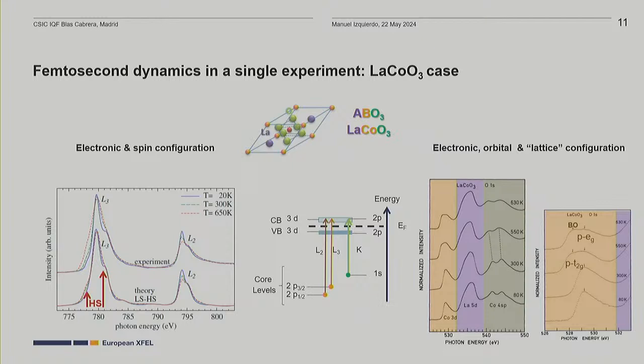more information, because basically if you have a perovskite ABO3, the first part of your oxygen absorption spectrum gives you information on the hybridization with the B atom, in this case cobalt. The medium part gives information on the A atom, in this case lanthanum, and the last part gives you information on the hybridization with the cobalt sp band that is linked to structural changes.